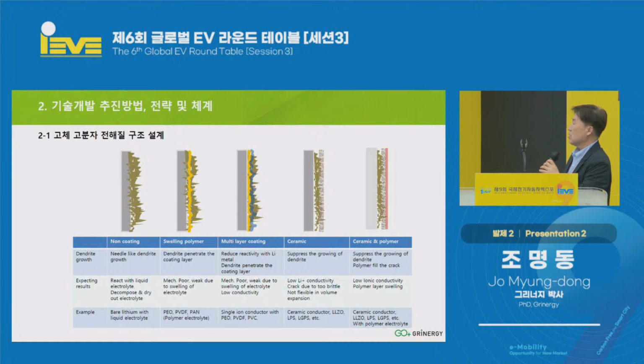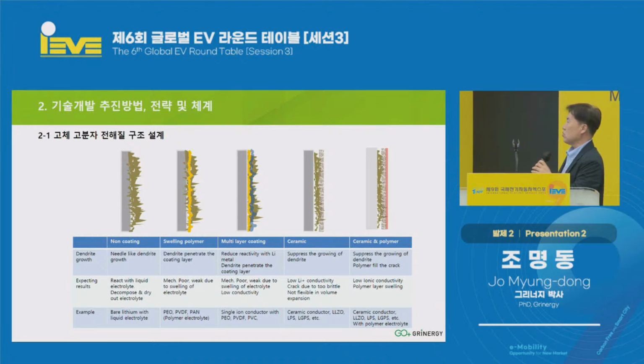So for many reasons, we have come up with a great methodology, but on top of the dendrite, we try to do the coating so that it can react with a liquid electrolyte, and such a system is not enough because the lithium will be penetrated and the dendrite penetrates the coating layer. Then another company came up with a new technology, multi-layer coating. When multi-layer coating is done, it can reduce the reactivity with the lithium metal, but the dendrite still penetrates. Nowadays, ceramic is being used to suppress the growing of the dendrite, or it can protect the conductivity.